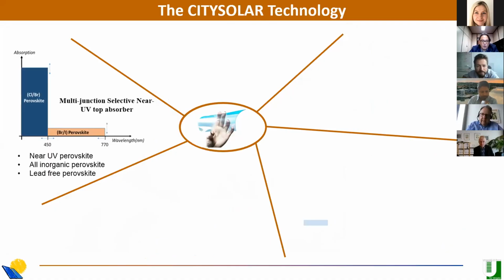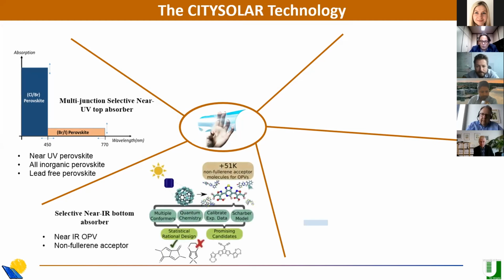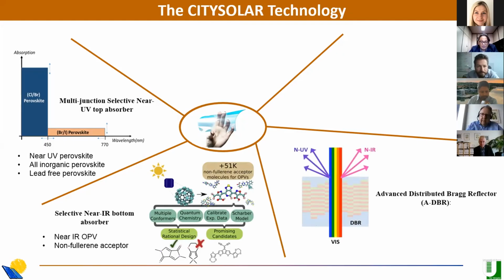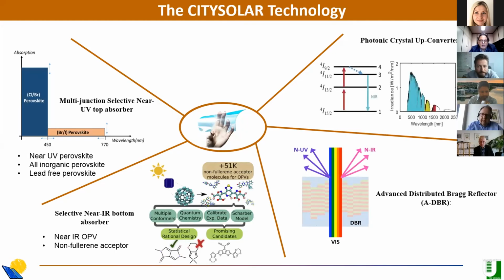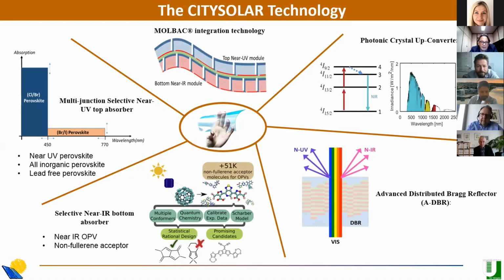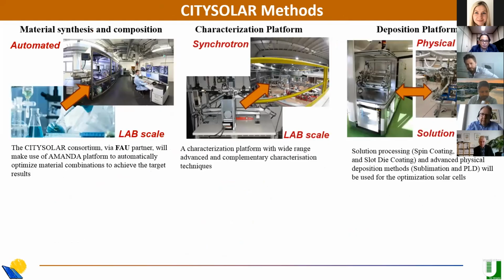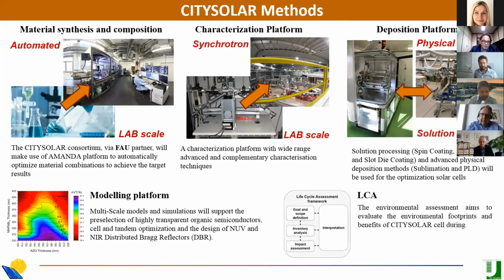It's based on quite robust technology. So we will use a near UV perovskite absorber, so that could also absorb a little bit in the visible range, but with a very low absorption. A bottom near infrared OPV absorber. We will have light management. Light management will be very important via DBR or up conversion, and this will be mainly done by Morten's group in SDU. And also we have a new way to integrate the top cell, the top module with the bottom modules, with the MOLBAC strategy. So we set up to do this with multi-scale facilities. We will use material processing, automatic material processes made in Germany, in FAU, with the Amanda platform. And so also for the characterization, we have a multi-scale characterization.